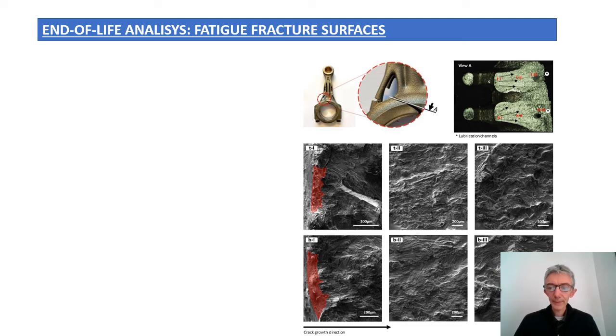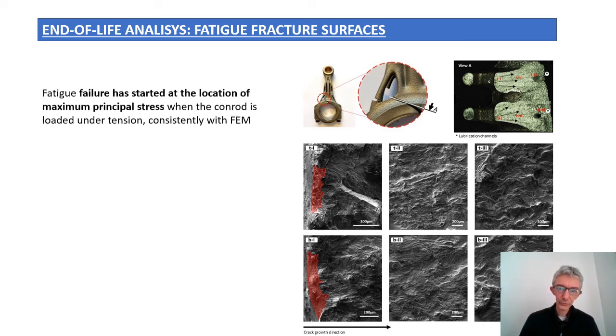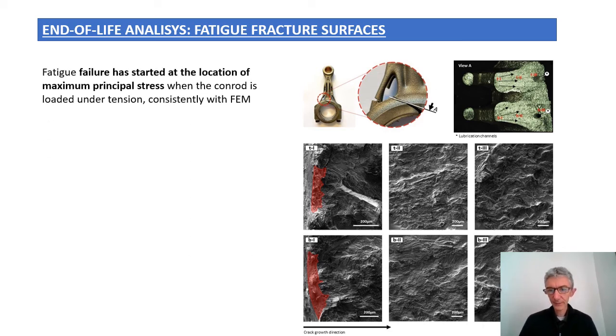Considering the results of fatigue tests, what is interesting is that there is a good agreement between the numerical prediction and experimental findings in terms of location of the failure, which mainly occurred in this area at the base of the connection between the central region of the conrod and the big end.